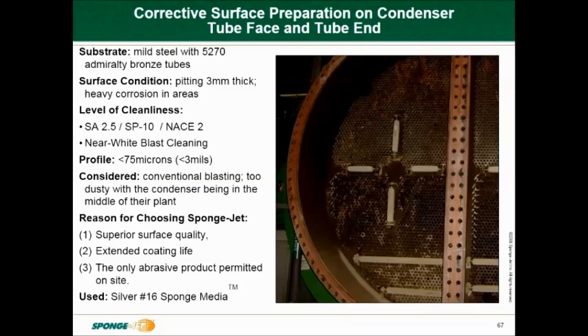Silver 16 was used to blast the substrate, 11 bags in total. That was 199 kilos to blast 25 square metres. That was 7.96 kilograms per metre squared. There was up to 3mm pitting on the tube face, and the tubes didn't need plugging, and that saved valuable time.